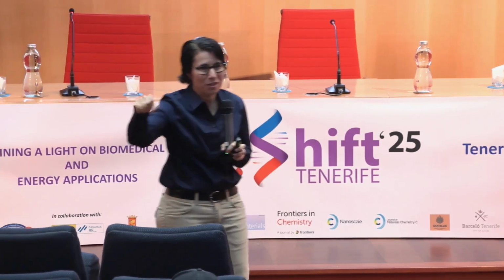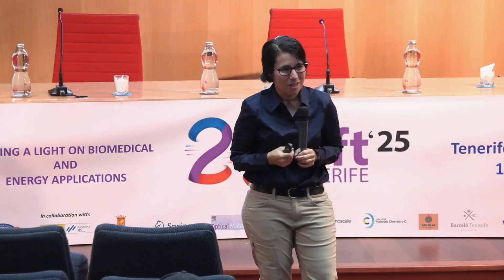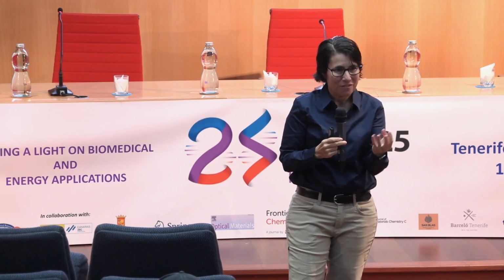In practice, we just have to find the right kind of orthogonal chemistry so that we don't end up with particles in solution. We haven't yet found the right orthogonal chemistries to do that. We only tried a little bit early on and haven't come back to it, but it's certainly a very interesting area. You have to choose the solvents and ligands correctly, because the particles have to stay on the surface to get them to bend. Then you could introduce ones that have optical switches that would change things. We've studied those in assemblies with the Murray Lab, who made them. You can have assemblies with optically or thermally addressable ligands and geometrically change the assembly. So it should work if we can get all the processing steps to work.